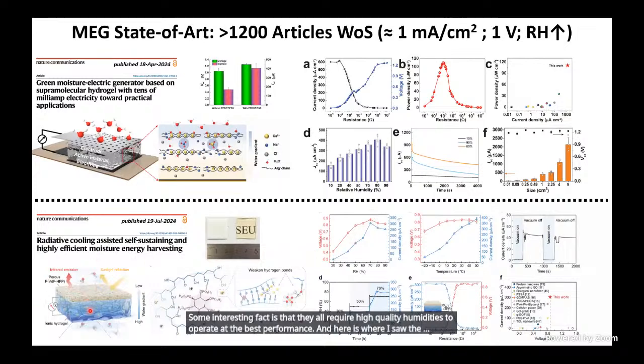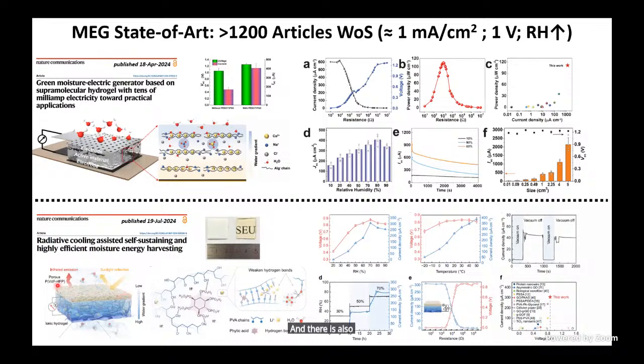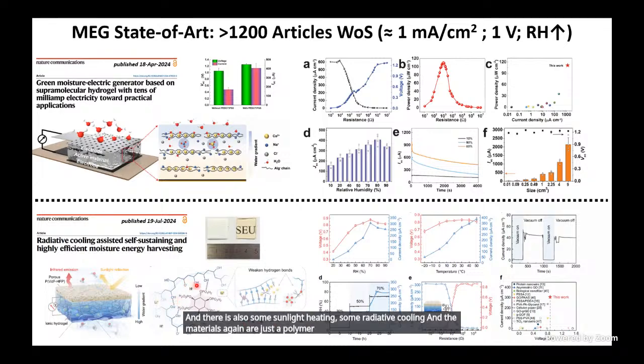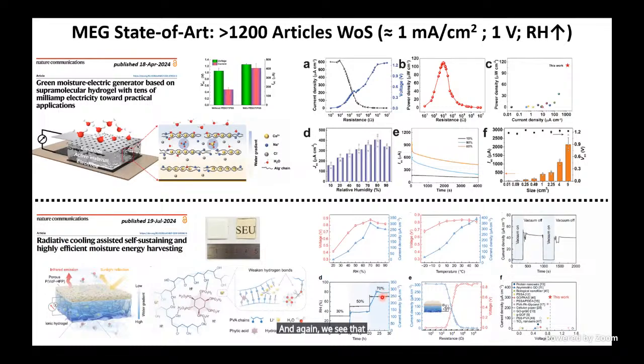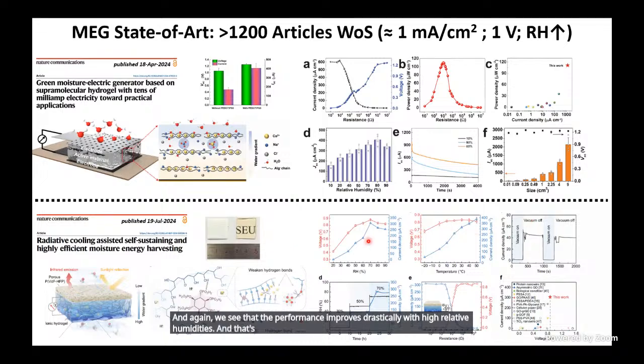Well, this is a different example where you see that they are implementing a new layer, which is an evaporative one, and there is also some sunlight heating, some radiative cooling. And the materials, again, are just a polymer, PVA, rich in oxygen groups, and also doped with another molecule which has a high density of phosphonic acid groups. And again, we see that the performance improves drastically with high relative humidities, and that's something which is common to all the systems.